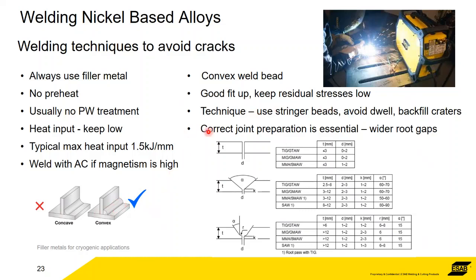Stringer beads, rather than weaving, really to reduce the heat input. The less time that you spend in weaving, the better. So stringer beads, more runs of stringer beads rather than one big weaved bead. That means you're putting less heat into it, and we're trying to keep the heat input low. Avoid dwell, we said here, and backfill craters.